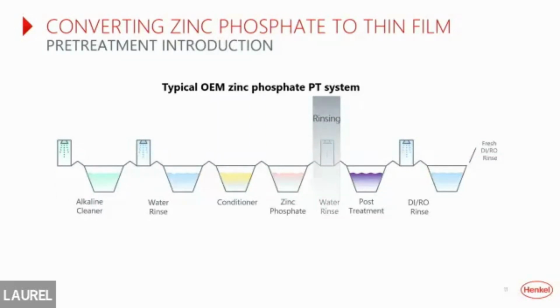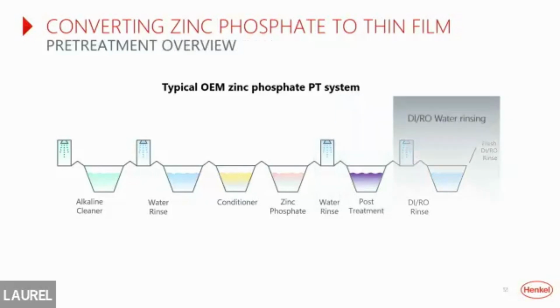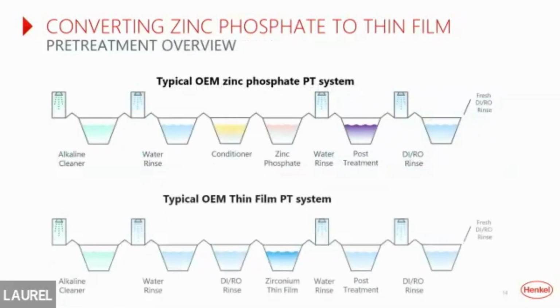And some customers use what's called a post-treatment or a sealer, which gives you a little bit extra measure of corrosion protection and helps fill in any gaps that were not done, or if there were any voids in the metal or voids in the zinc phosphate coating. And finally, we go with either DI or RO water rinses. So this is fairly generic. Now, when you juxtapose that to a